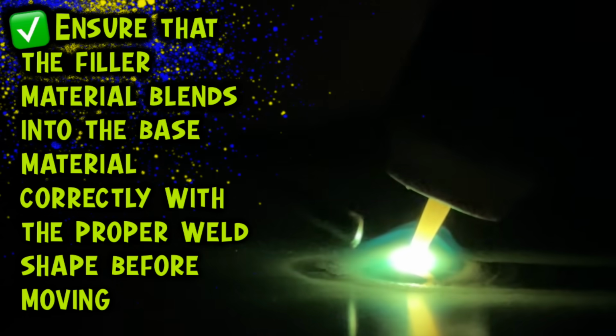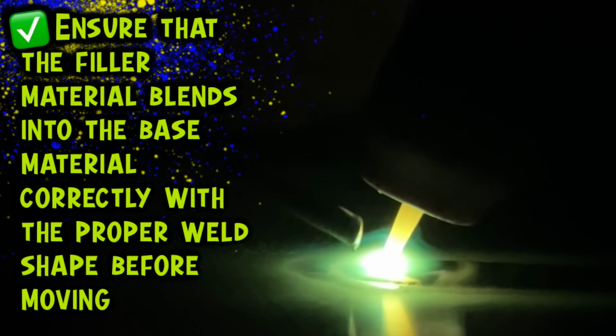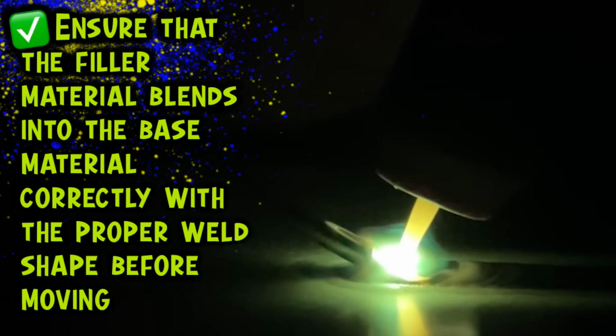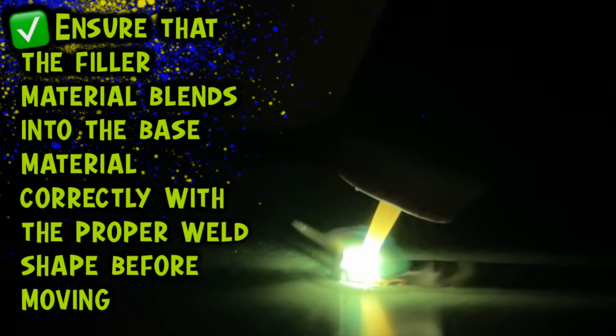This is pretty common when working with aluminum. A lot of people feel pressure to get going right away out of fear of burning through the material. Without the time spent to adequately develop the puddle at the beginning of the pass, this is essentially a puddle that has not been developed properly before somebody tries to start moving it. It takes a little bit of time at the beginning, a little more attention to detail. We want to make sure that the filler material settles down correctly and the profile or shape of the weld is exactly what we want before we move away from the start.